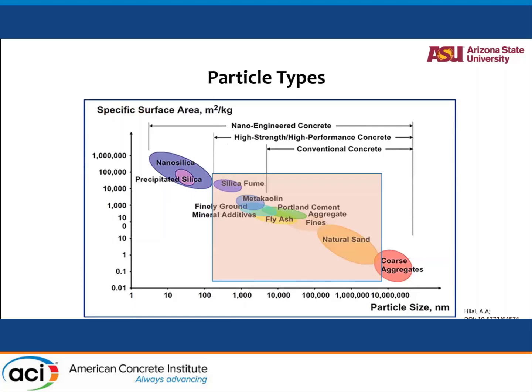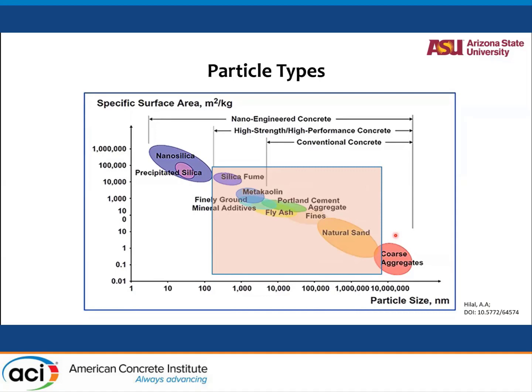Okay, so particle types, if you look at it, you have the range of particles all the way from nanosilica, which is a few nanometers, all the way to coarse aggregates, which are a few millimeters. So you have about 6 orders of magnitude of sizes within the materials that you are using. The shaded area that I'm showing here is pretty much all the materials that we have used, right from silica fume all the way to some size of coarse aggregate, not the entire coarse aggregate size, but some size of coarse aggregate until about, I think, 6.5 millimeters or so.